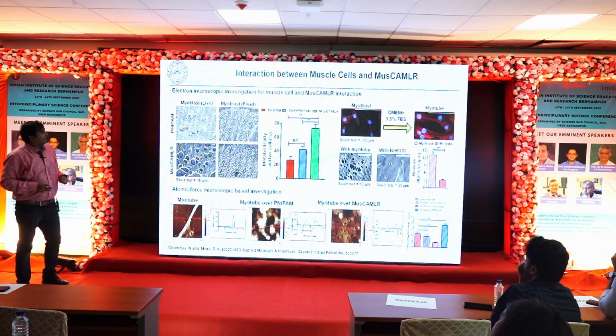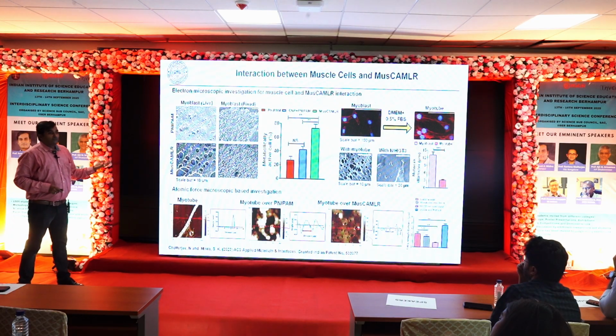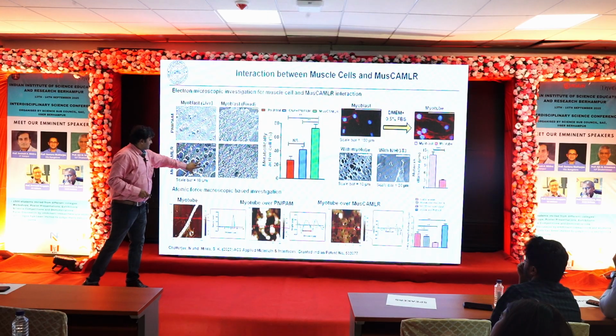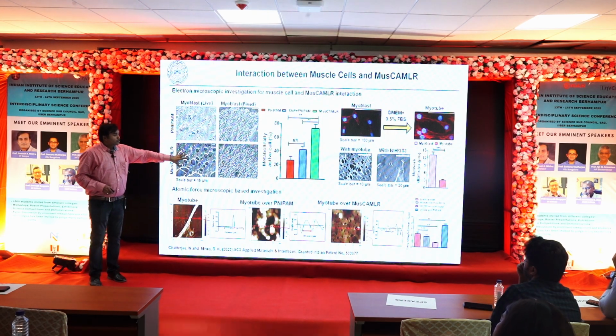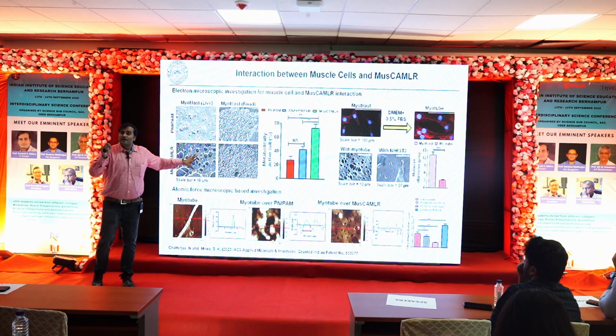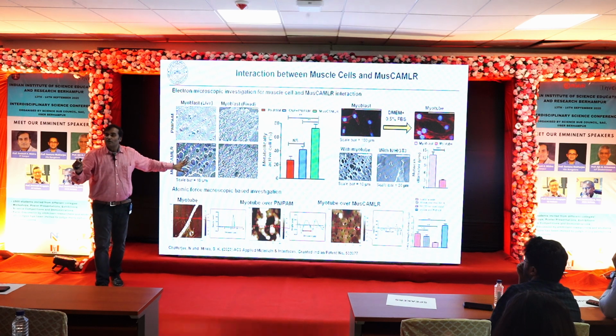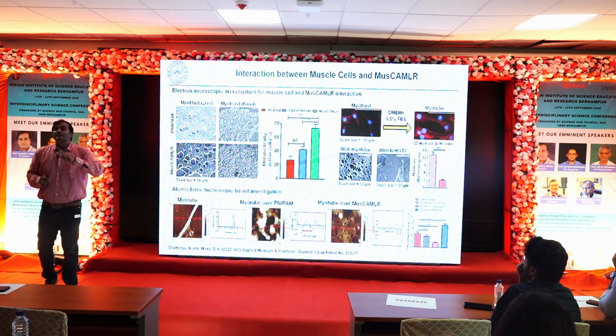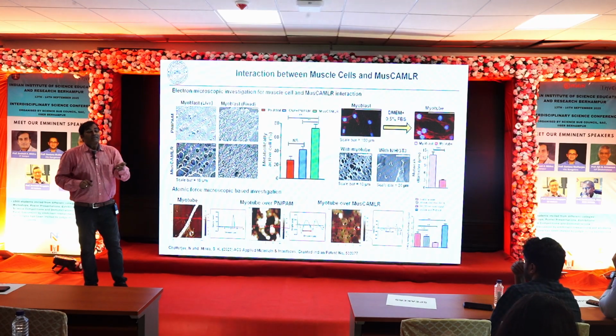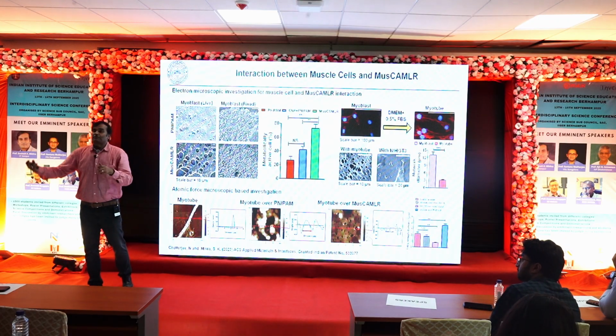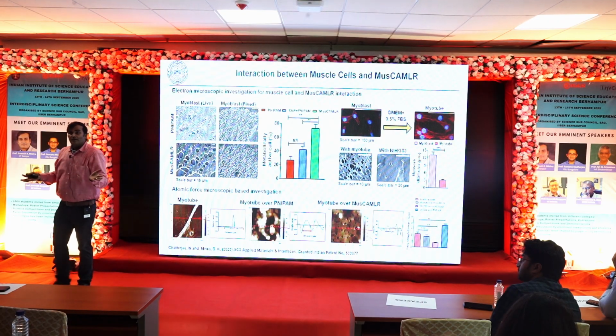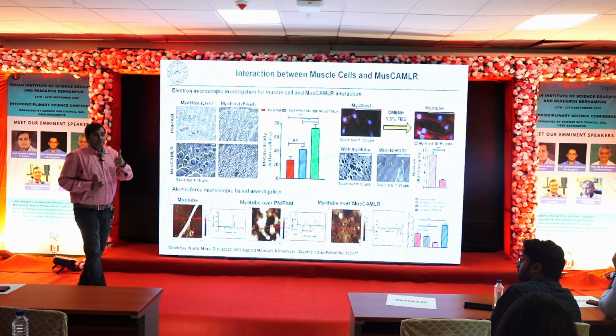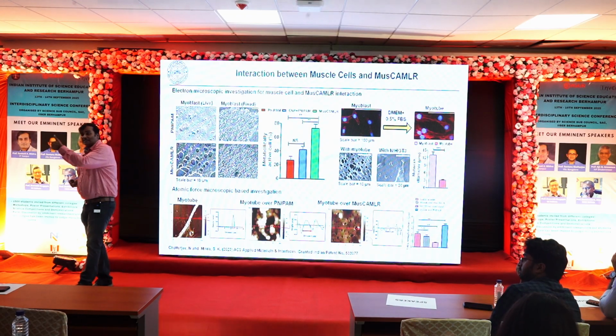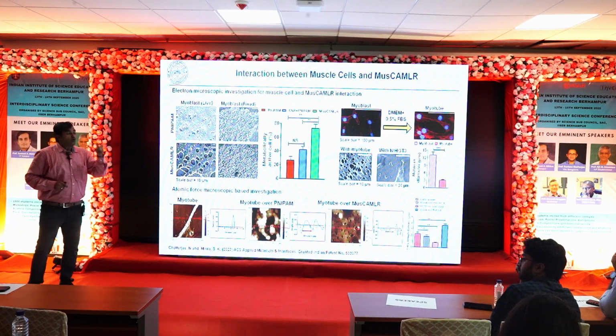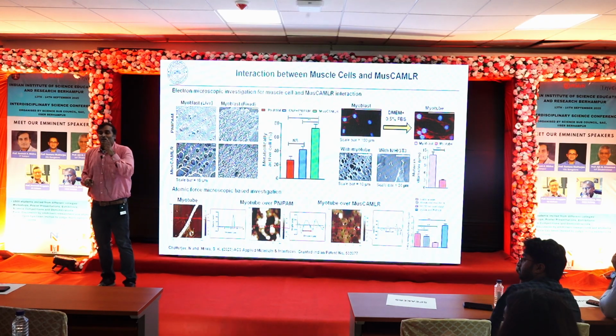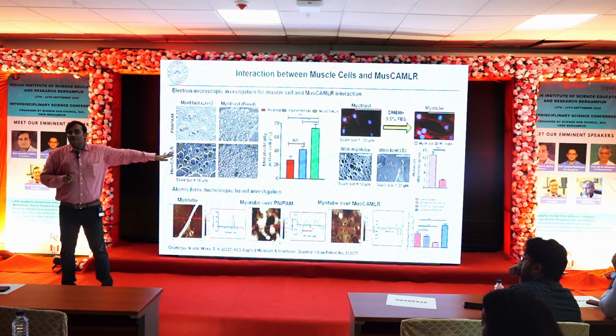Then we wanted to look in scanning electron microscopy at what kind of network they are generating. You can see the uniqueness of this network, which was only found when they were in interaction with muscle cells. We tried to put some fibroblast cells and they did not create the network. That was a very unique thing. Second, we took dead cells and put them there, and it again did not make the network. So we got two pieces of information. One, that it is very specific to muscle-like cells. Second, it works only with living forces. If the system is non-living, it doesn't make that kind of network.